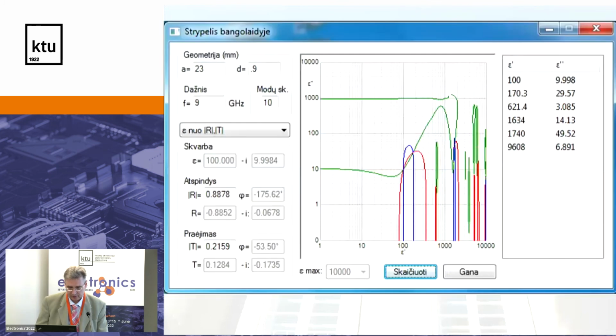So waveguides I will skip, only to show that if you measure reflection and transmission, there is not only one solution. If you solve mathematically reflection and transmission, these formulas, you are getting where the green, blue, and red lines intersect with each other. These are the solutions. And from measurements at 10 gigahertz, oh, sorry, 9 gigahertz, and you take only 10 modes, the same as we used in the coaxial line multi-mode approach, we are getting the values which satisfy.